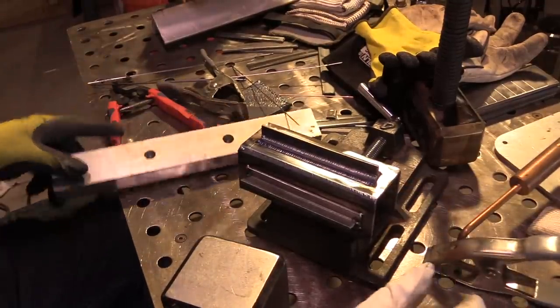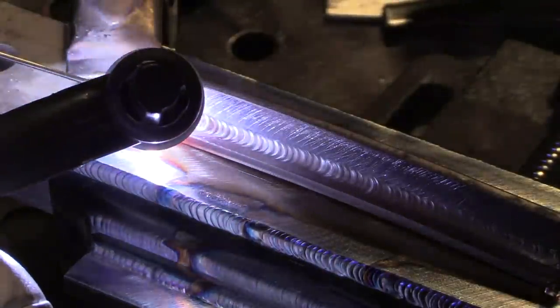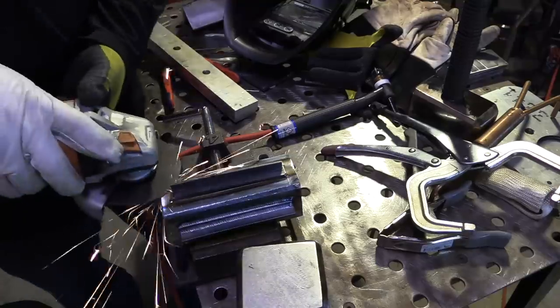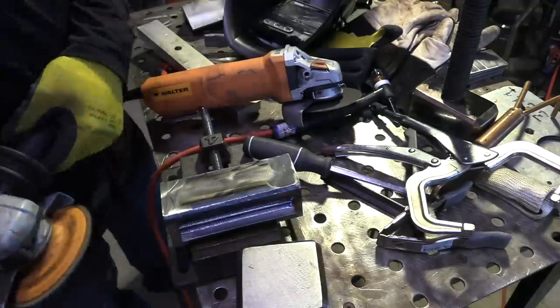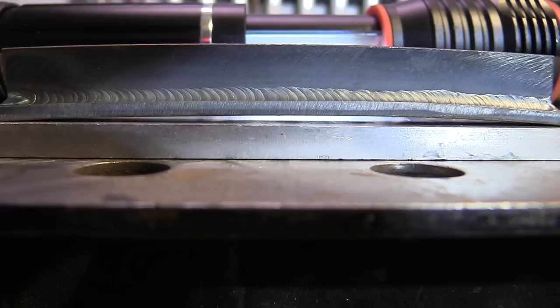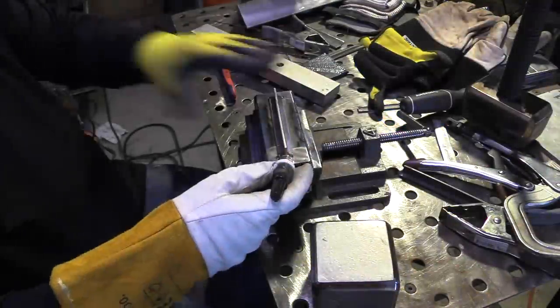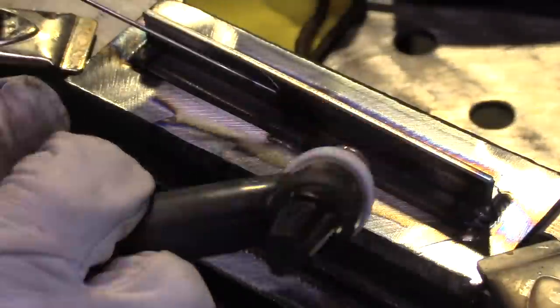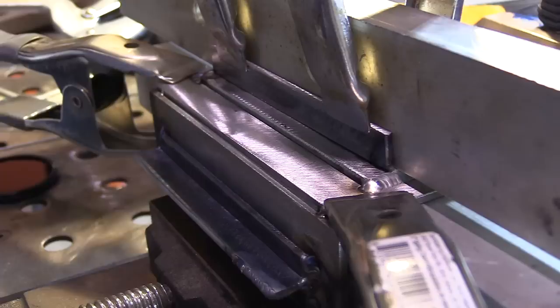Okay, well that's all three welds. Let's talk about some mistakes that we can make. I'd like to say I did this on purpose, but I just wasn't thinking and I did the wrong sequence and welded the T-joint before the lap joint. And look what happened there. If I'd had enough tack welds on it, it might have been okay, but there was no tack in the middle there. It got so hot, it bowed way up. And really the only thing to do was just cut it loose and tack a new piece on there. Now, I could have possibly salvaged it by heating it up and C-clamping it and all kinds of things like that, but it wasn't worth it. That's quite a bow right there. All right, so again, put some small fusion tacks on here, something smaller than the final weld will be. And then a little bit of filler rod on the ends of that T-joint. And this time I'm going to tack in the middle on both sides and then I can weld that T-joint first by doing that without it bowing up.